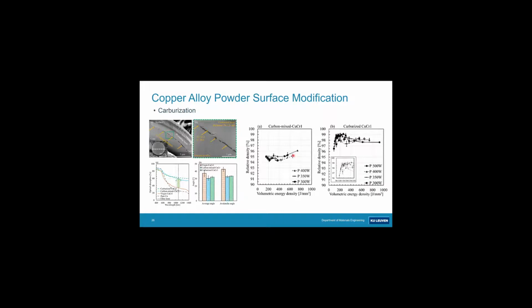So if you compare the processing conditions for the pure carbon mixed copper chromium 1 powder and that powder with additional heat treatment to form carbides, you see the processing behavior here. We compared similar power levels, up to 400 watts, and very slow scan speeds, resulting in very high volumetric energy densities, we could maximum achieve parts with 96% density. While if you do the same, even at much lower volumetric energy densities, which means at much higher scan speeds, we have a fairly broad processing window where we can sustainably process these carburized copper chromium 1 powders.